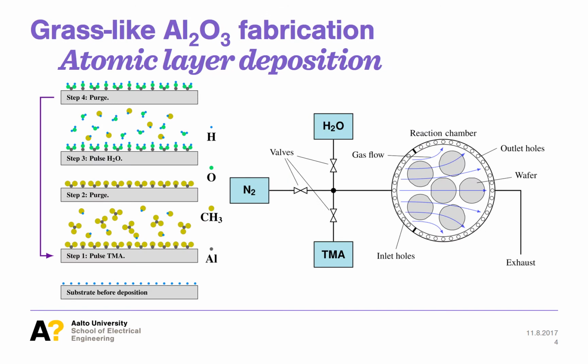The first step in grass-like alumina fabrication is atomic layer deposition, or ALD, of aluminum oxide. Atomic layer deposition is a thin film growth technique which involves consecutive saturated surface reactions of 2 or more precursors separated by purges of the reactor. For the growth of aluminum oxide, the precursors are trimethyl aluminum, or TMA, and water vapor.